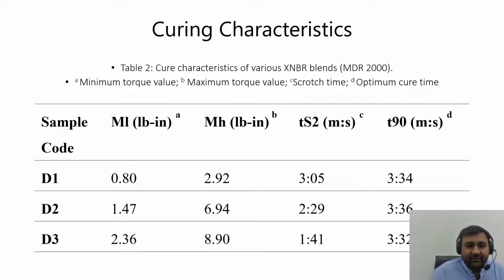So these are the curing characteristics of the XNBR blend which was prepared of the three samples. And the table shows that with the addition of higher concentrations of carbon fillers, higher minimum and maximum torque values are achieved. The results show that scorch time and optimum time are reduced with the addition of carbon fillers, indicating a strong interaction between the fillers and the rubber. This is also linked to the viscosity of the compound, suggesting an increase in the viscosity and hardness with the addition of carbon fillers. So the torque is increasing with the increase in hardness, and the scorch time is reducing with the increase in the hardness of the rubber.